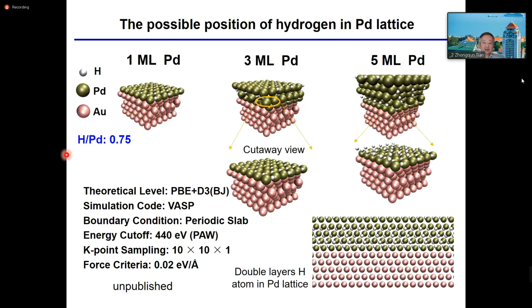And so we took this sample and asked another co-worker, Professor Sai Duan, to simulate this system and see what the location of hydrogen is. As you can see, it's quite interesting. For the one monolayer, the hydrogen is not on the top side, but in the hollow site.